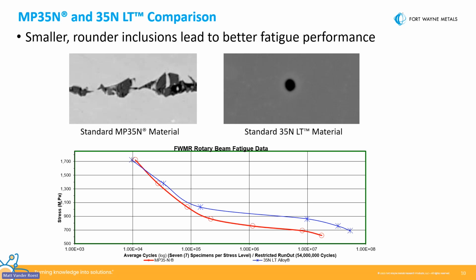Not only is the inclusion much smaller than what we find in MP35N, but the shape itself significantly reduces the propensity for stress risers within the material. As evidenced in the chart, you can see the red trace is for MP35N. The blue trace is for 35NLT.